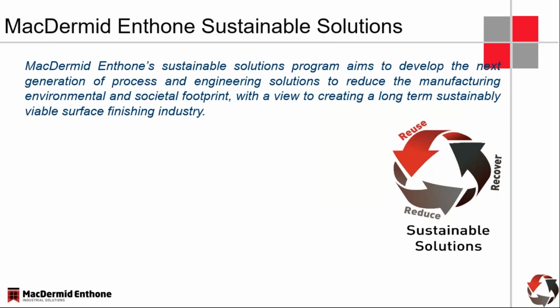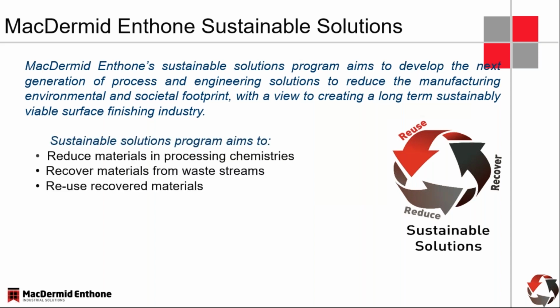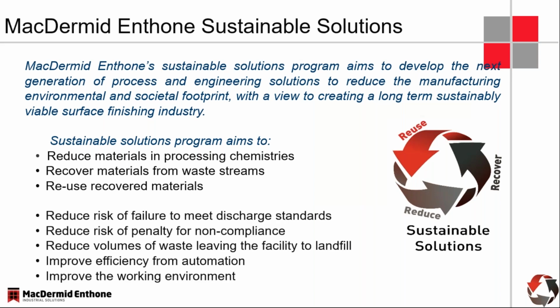So one of the things that MacDermid Enthone has started to put forth is a very significant sustainable solutions program. And what we do with these sustainable solutions, you can see that, we try to recover waste streams. We try to reuse materials. We have solutions to pull copper and/or nickel and/or chrome out of rinse tanks for POP lines. It's a tremendous savings for folks. If you don't have to keep adding nickel sulfate or nickel chloride, and you can reclaim the nickel in a drag out, that's a savings right down to the bottom line for purchases of nickel metal. And that's a tremendous amount of reduced sludge in your waste stream.